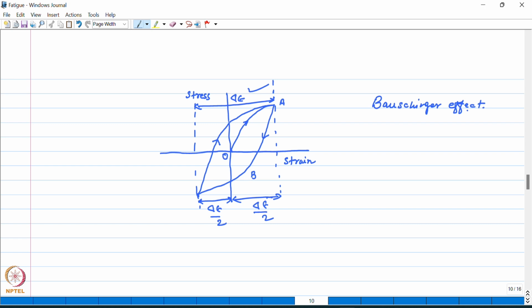And you can also note that the total strain consists of an elastic strain, delta epsilon E, and a plastic strain, delta epsilon P. So the total strain delta epsilon T is equal to elastic strain delta epsilon E plus plastic strain delta epsilon P. The material may go cyclic hardening or softening or may remain stable, but ultimately during the deformation process a stage will be reached where stable stress strain loops will be developed.